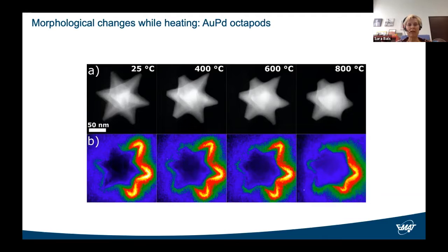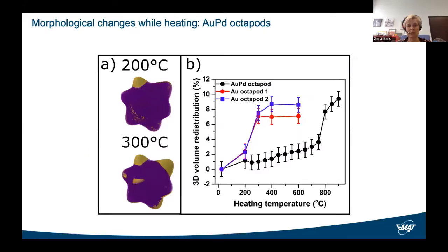We also compared these results to the thermal stability of pure gold octapods, and that is illustrated here for 200 degrees Celsius and 300 degrees Celsius. And in the graph, you can also see indeed that the pure gold octapods in red and blue are much less thermally stable in comparison to the gold palladium. So the palladium really adds to the thermal stability of these systems.